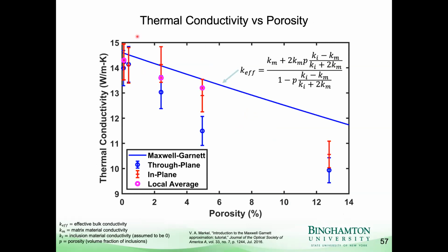Next, we want to analyze the thermal properties versus porosity. So here's the same data presented versus porosity, and we can see that the porosity explains a lot of the reduction in thermal conductivity, especially for these high porosity samples, but it doesn't fully explain the reduction in thermal conductivity. So that was somewhat mysterious. So why is it much lower than we'd expect from porosity?